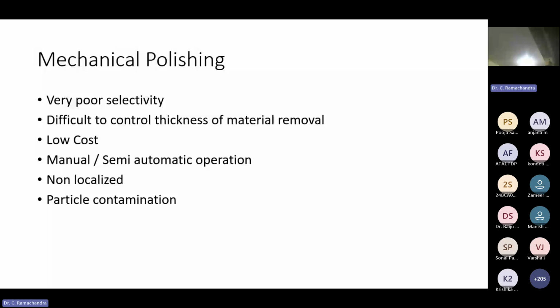It has very poor selectivity. It does not bother whether it is silicon oxide or silicon nitride. It just removes whatever comes on the way. So very poor selectivity. Therefore, it is useful only when selectivity is not at all a criterion. You just need to thin the sample by a few microns. It is okay. It is low cost.